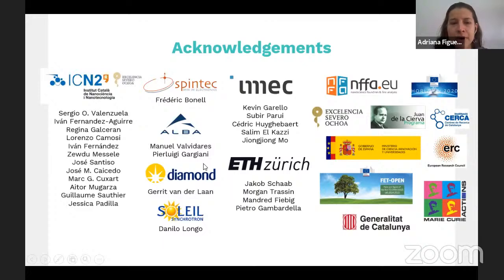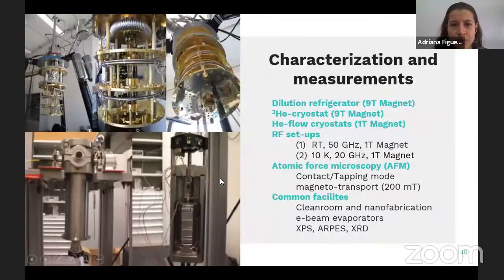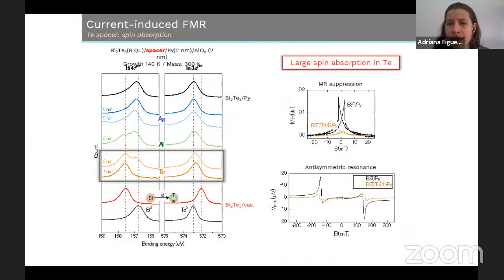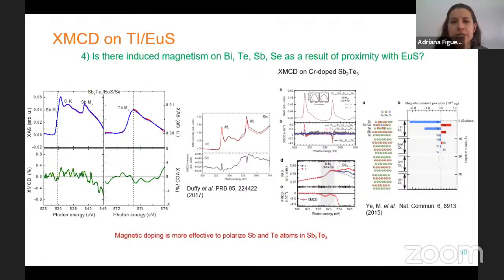Yeah, I understand your point. The core levels that we explore on the TIs, for example on antimony or tellurium, have been demonstrated to show magnetism in other kinds of systems. In this family of TIs, like antimony telluride or bismuth antimony telluride, when we dope these materials with magnetic atoms, for example chromium or vanadium, or even manganese, these core level transitions have revealed that they become polarized with these magnetic atoms. So that's why we said, okay, there is this precedent.